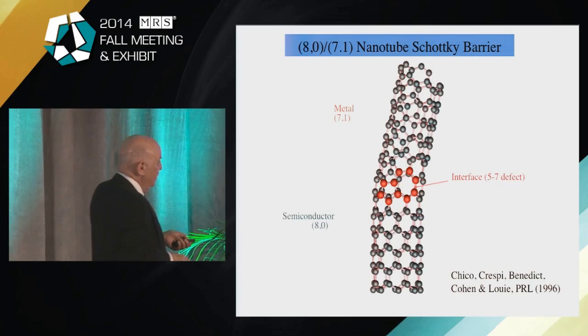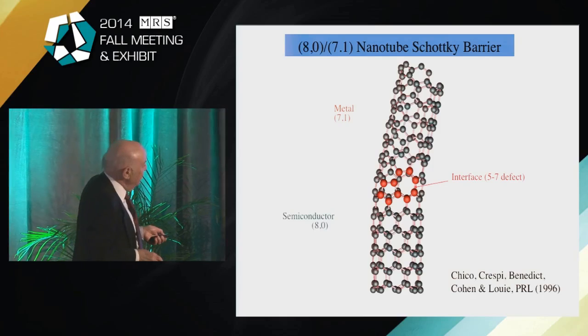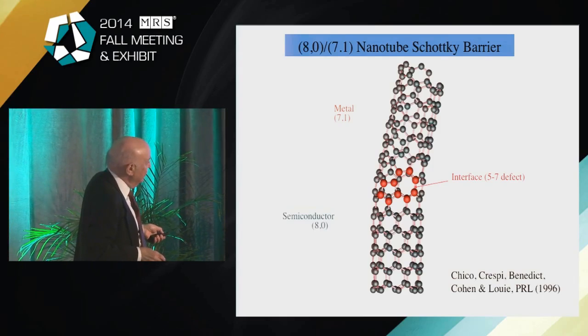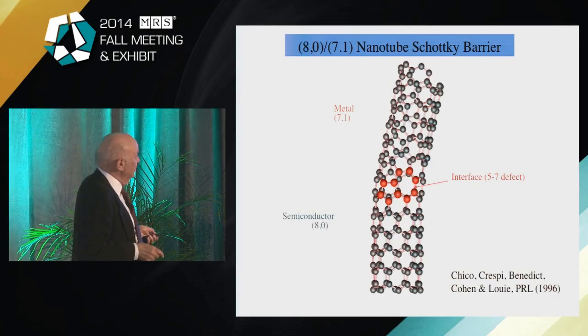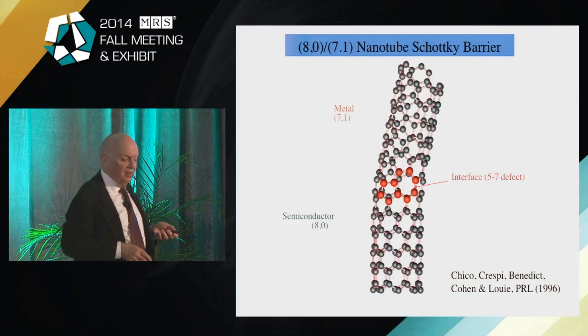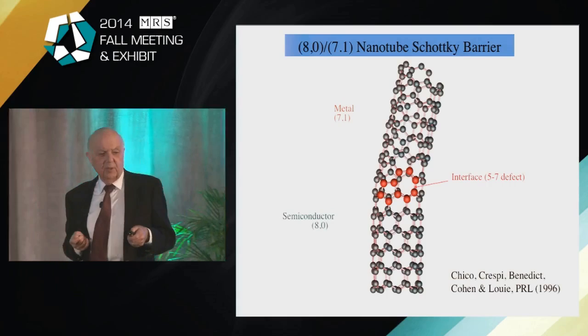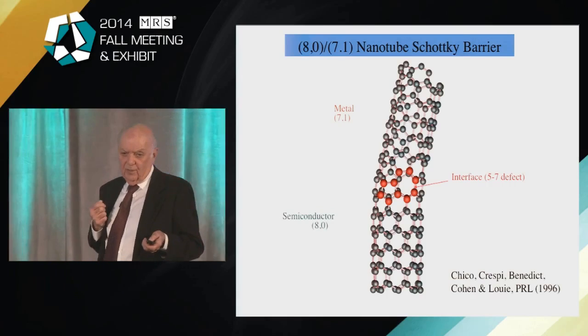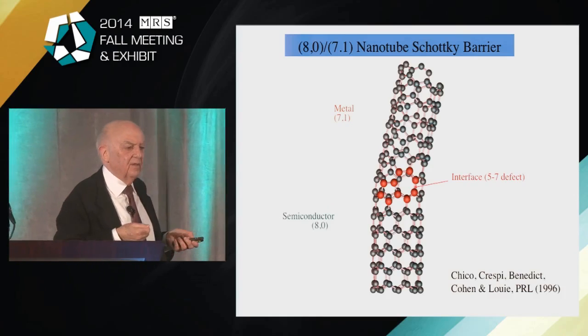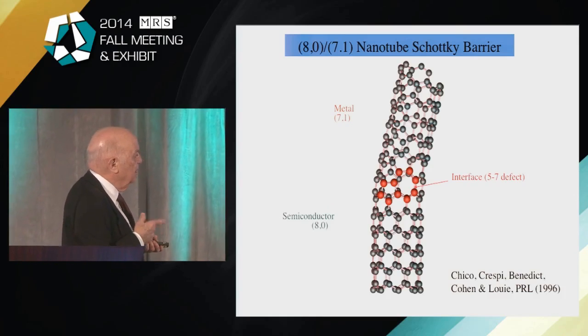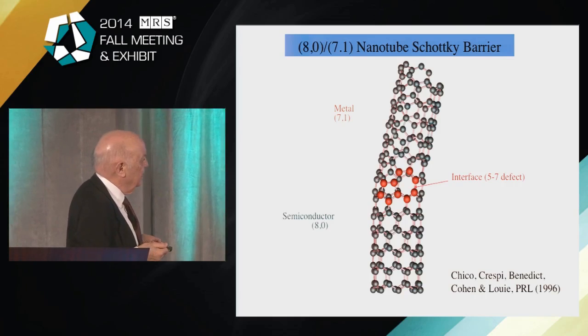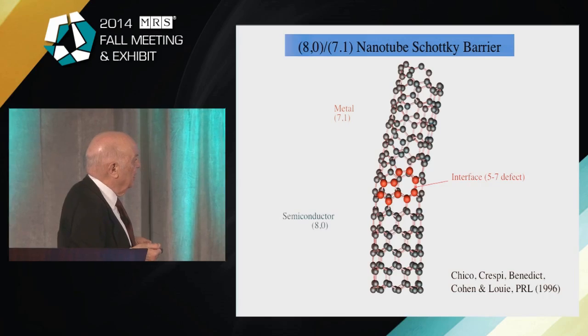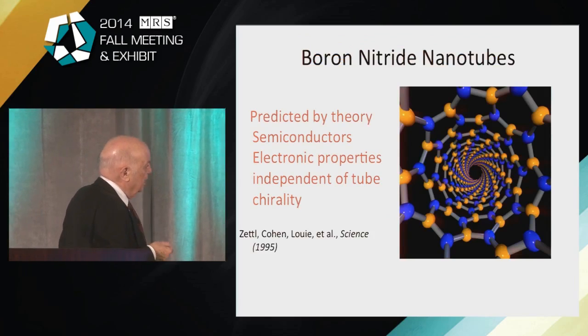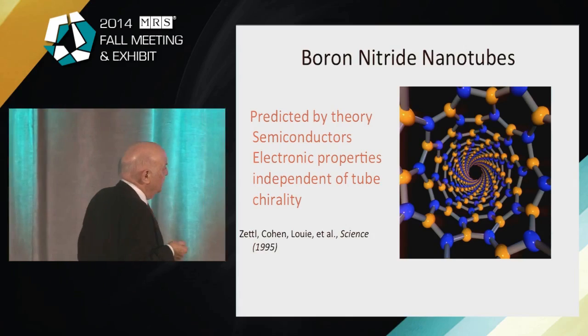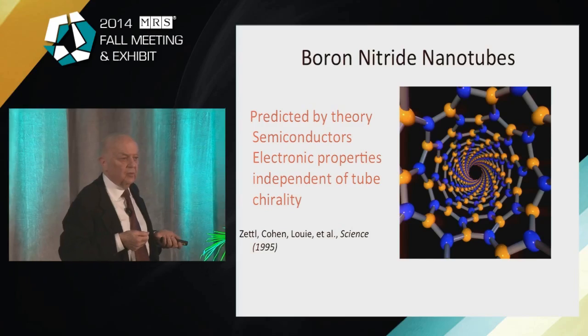And you can put the 2 of them together so that you have a defect, which instead of 2 6-fold rings, you have a 5-fold and a 7-fold. So now you have a semiconductor in contact with a metal, and it acts exactly like a piece of silicon in contact with a piece of aluminum. However, think about how small this is. And so you can make devices on a very, very, very small scale. And this system was predicted theoretically, and fortunately, experimentally it was found. And this is another one of that kind. We were able to predict that boron nitride would form nanotubes.